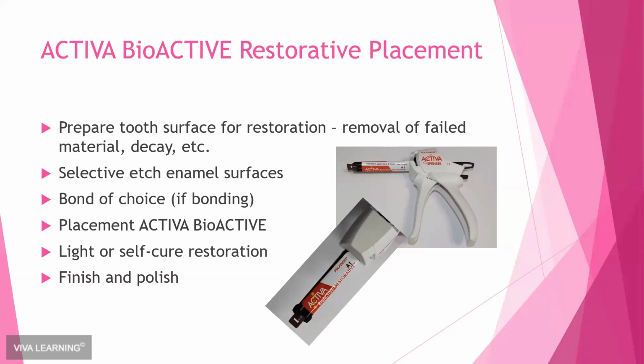So when we're placing this material, you're going to prepare your tooth structure as you normally would, obviously removing failed material, decay. I like to do some sort of a retentive preparation. I tend to use a pear burr, whether it be a diamond or a carbide burr, because I like to have a little bit of mechanical retention. I'm not talking G.V. Black, really hard cuts, but a little bit of mechanical retention is always a good thing.